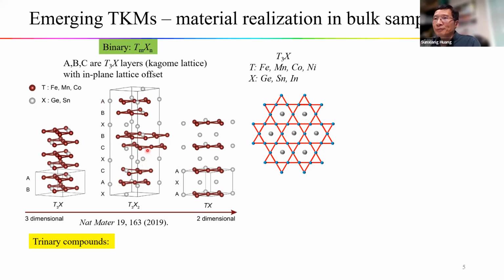In between the bilayer Kagome lattice, there are these X layers with honeycomb structures. So these are the 3-2 structures. For the 1-1 structures, these Kagome layers are stacked with single layer separation of these X layers. So they have the stacking like A, X, and A. From 3-1 to 1-1, the separation between the Kagome layers increases. So the 1-1 material is closer to the two-dimensional limit.